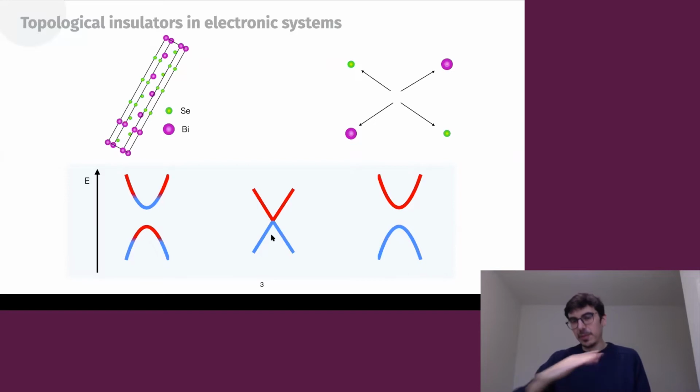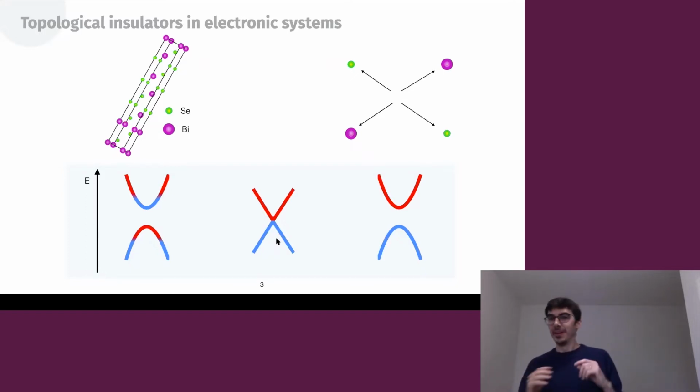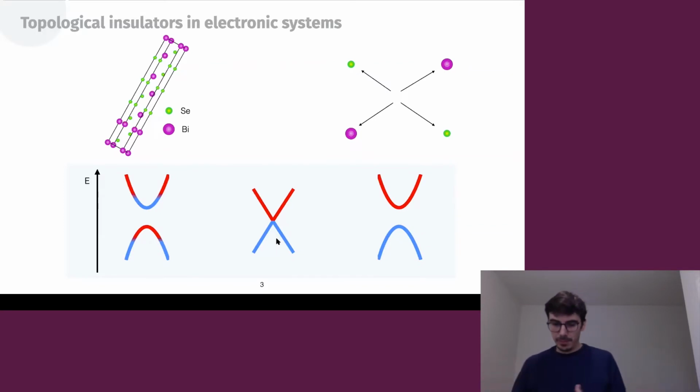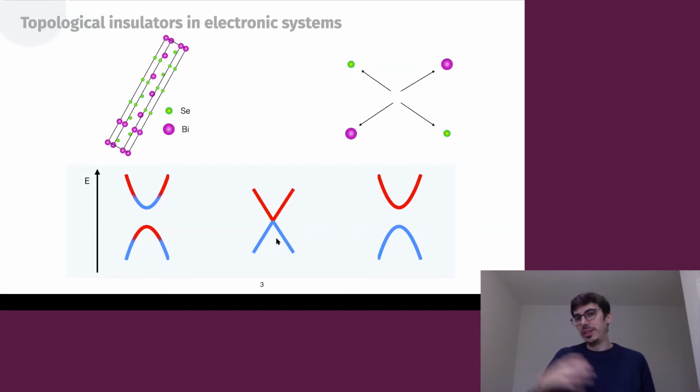So the surface of the material must be the point shown here in the middle of the diagram where the wave function twist becomes undone. So that means that the surfaces of topological materials will have some sort of interesting metallic state associated with them. And that state has some interesting features because it's determined to be there by the underlying topology of the system. This general relationship between a bulk topology and the surface state or boundary state is called the bulk boundary correspondence.